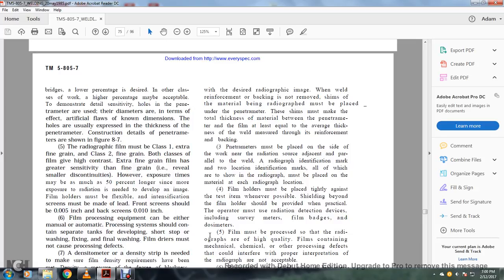When the weld reinforcement or backing is not removed, shims must be placed under the penetrameter. The shims must be made so that the total thickness of material between the penetrameter and the film is at least equal to the average thickness of the weld, measured through the reinforcement and backing.